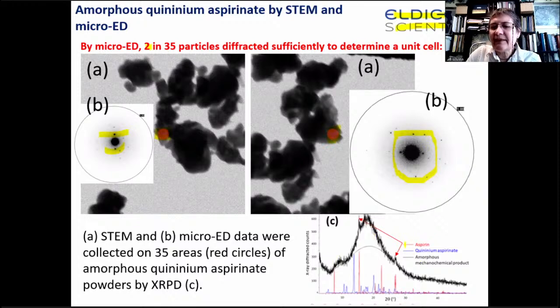And we can see that there are 2 little peaks, one here and one there, but they correspond to the diffraction pattern of aspirin. So there is unreacted aspirin that is left over in that material. So then, which was the structure of these particles that diffracted?